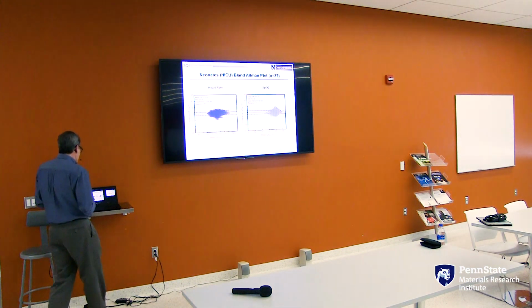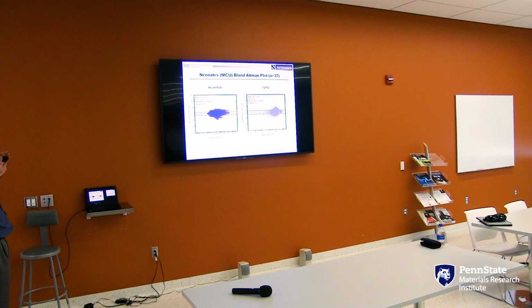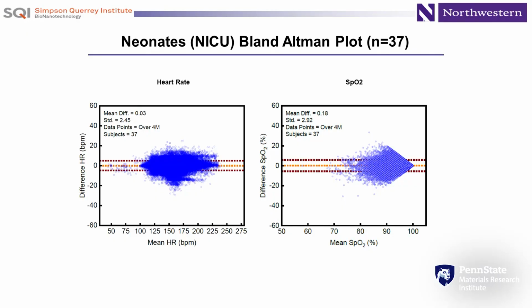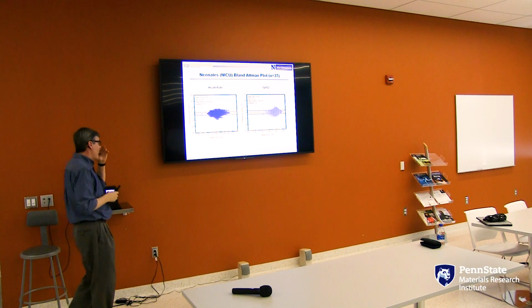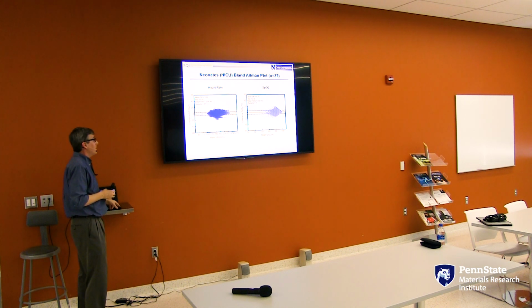So we're pretty deep into these studies. This is the kind of data, I mean, it's big data by any definition. This is just extracted heart rate from the ECG waveforms and SpO2 from the PPG waveforms. So this is just a tiny fraction of the total amount of data that we've collected. These are 4 million data points, both on the left and the right. And these are Bland-Altman plots. It provides a way to look at the degree of agreement between our measurements and clinical gold standards, very tight, so well within the kind of variance that the FDA looks at for proving new device technology. These are not FDA approved, but we're moving in that direction.